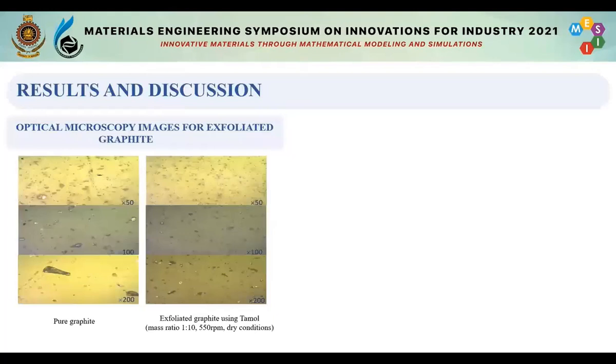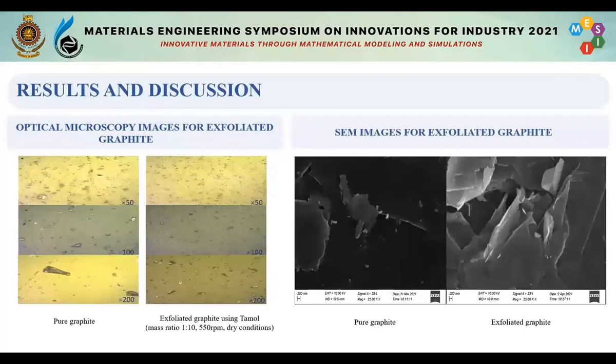This optical microscopy image shows how the dispersing ability of graphite has been improved by exfoliating it using Tamol. And the SEM images of pure graphite and the exfoliated graphite clearly show how our exfoliating process has impacted the graphite sample. The right-hand side SEM image shows how the thick layers of pure graphite have been reduced into thin layers by the exfoliation technique.